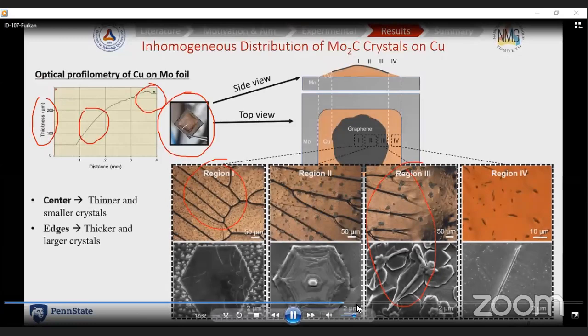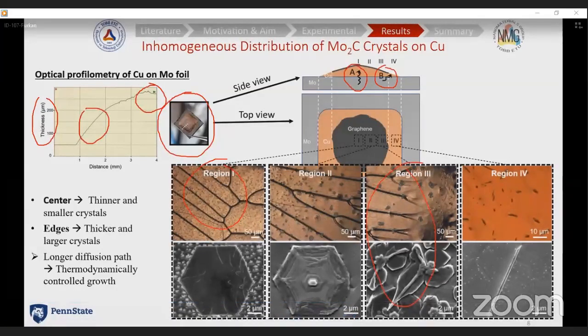And to understand the mechanism of this, we need to examine the diffusion path of Mo species. So there are basically two different diffusion paths for the molybdenum species, one of which is through the center of the copper and the other from the edge of the copper. And since graphene first forms, the A path is not quite possible because of the very high activation energy of diffusion of molybdenum through the graphene interface.